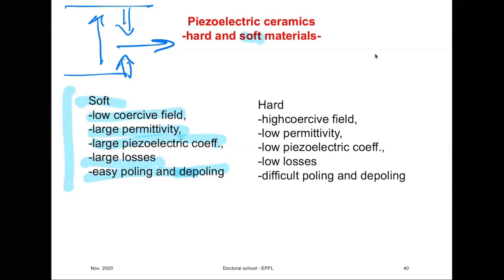And this easy motion, displacement of domain walls under external forces, makes materials have a large piezoelectric coefficient, large permittivity, to be mechanically soft, to have large losses, both dielectric and mechanical, and to be easy to pole and depole, with a low coercive field.